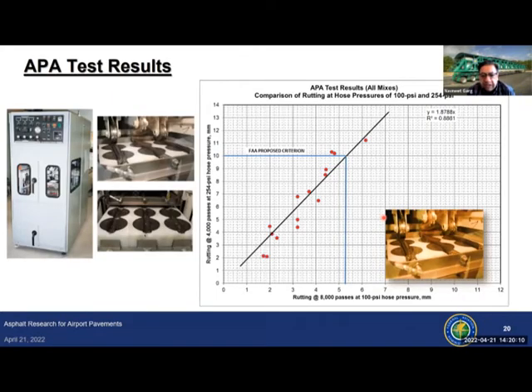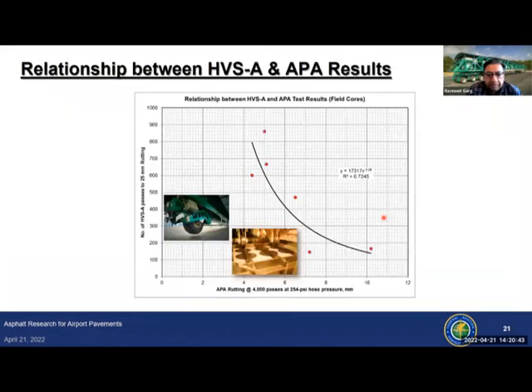And what you see on this chart is the relationship between APA rutting with 250 PSI hose pressure and 100 PSI hose pressure. And that's the data that we used to come up with a criteria for 100 PSI hose pressure. So if you have 250 PSI hose pressure, the rutting at the end of 4,000 passes was limited to 10 millimeters. And if it's 100 PSI hose pressure, then it was limited to 5 millimeters at 8,000 passes.